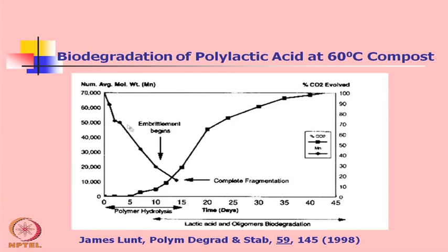You see the molecular weight has come down from 70,000 average molecular weight to almost 10,000 molecular weight fragments. And it shows almost complete biodegradation, 100% biodegradation in 40 to 45 days time period.